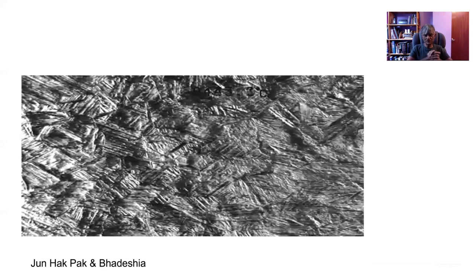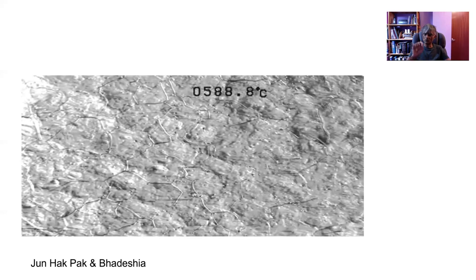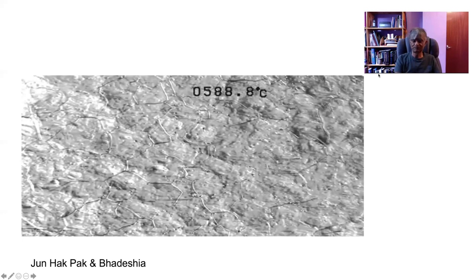Okay, so that is the shape deformation on a scale which is optical, because each one of these austenite grains, which are identified by the thermal grooves, is of the order of 20 micrometers in size. So over there, we are not looking at the shape deformation of an individual platelet, but a cluster of platelets with all the residual phases in between. So it can be misleading, okay? The literature is full of statements which are drawn from observations on a coarse scale.